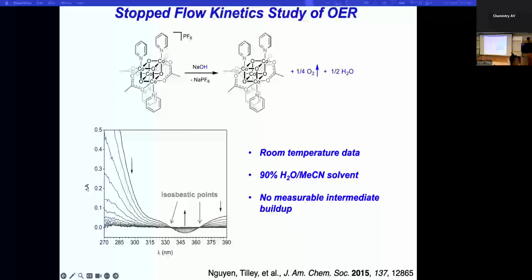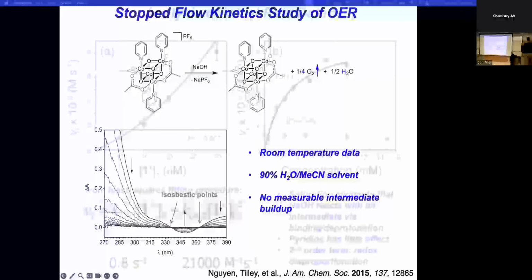And this is a very fast reaction, but we found that we could study it by stopped-flow kinetics. And here you see the UV-vis data that were used to establish the kinetics. We see two isosbestic points. And this is room temperature data in water acetonitrile. So there's no apparent buildup of an intermediate.